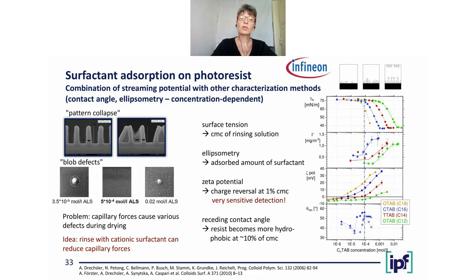And the idea was to rinse the photoresist structures with cationic surfactants after the development. And to find out how this works, we again applied various methods. We measured the surface tension of the solution. This is the top image. We measured the adsorbed amount of surfactant on the photoresist. And we also measured the Zeta potential and the contact angle of the photoresist after the deposition of the surfactant.